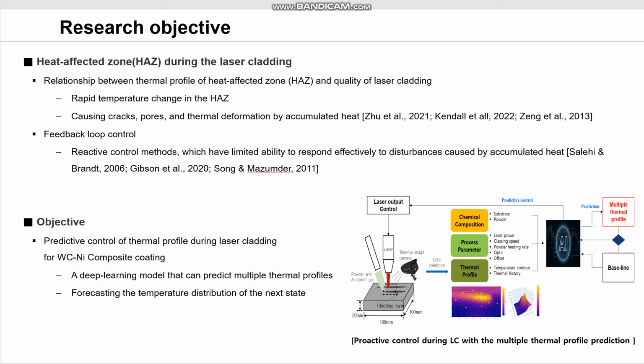During the laser cladding process, a laser beam is irradiated to the surface of the substrate, and then the alloy layer formed between the substrate and the powder is rapidly heated and cooled. The melting and solidification of the melted pool results in rapid temperature change in the heat effective zone. As a result, pores, cracks, and thermal deformation can occur. So, the accumulated heat in the heat effective zone must be properly controlled during the laser cladding process.